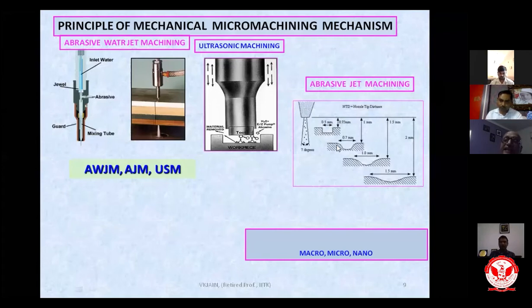And depending upon the value of the nozzle tip distance, the shape of the cavity being created is changing. As you can see here, when the nozzle tip distance is 0.75 millimeter, you are getting a quite straight-sided cavity. But as you increase it to 1 millimeter, 1.5 millimeter, 2 millimeter, you can see the change in the shape of the cavity being formed. Width is increasing, depth is decreasing as you are increasing the nozzle tip distance.